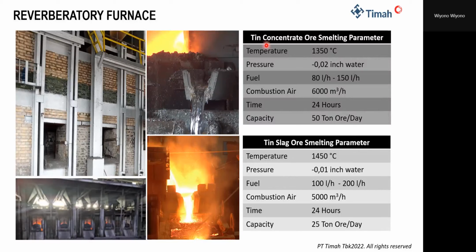And this is the parameter of tin concentrate smelting. The temperature is around 1350, and the pressure is minus 0.02 inch water gauge. This parameter, especially the pressure, comes not only from the reference but also from our experience in smelting. And then there's the fuel, combustion air, and then the time for smelting is 24 hours to smelt 50 ton of tin concentrate.